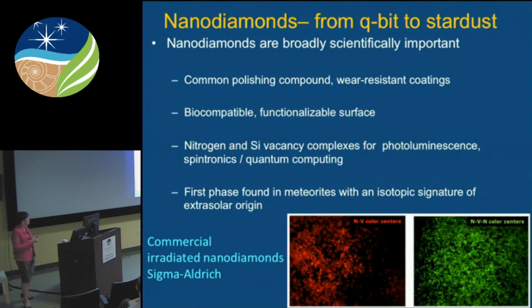So you can chemically modify the surface to attach other species of interest. And furthermore, you can make it both magnetically and optically active depending on which impurities and which defect structures you incorporate into the nanodiamond. So both nitrogen and silicon vacancy complexes are exploited for photoluminescence and for potential use as spintronics or quantum computing qubits, so-called.